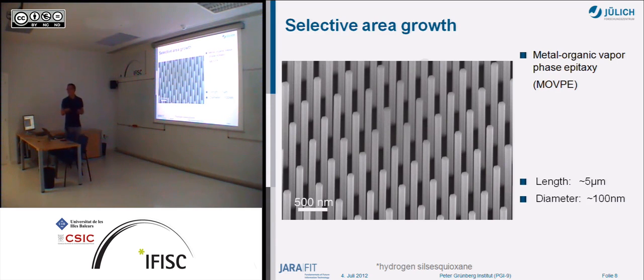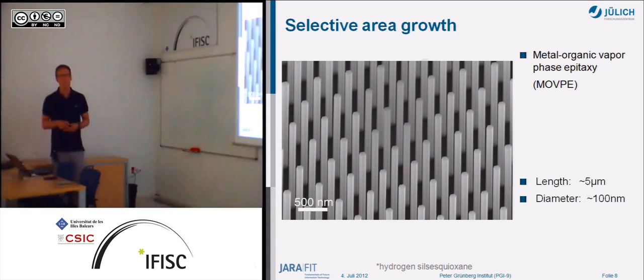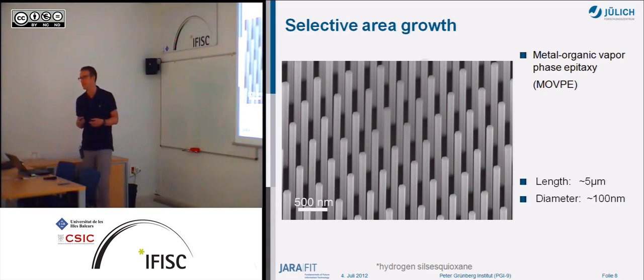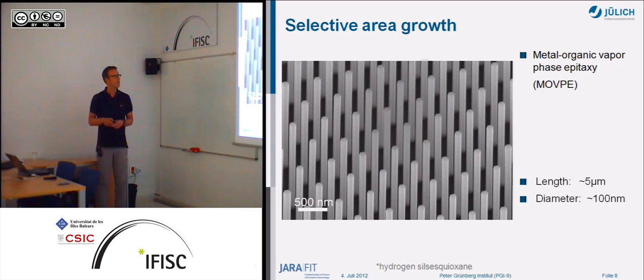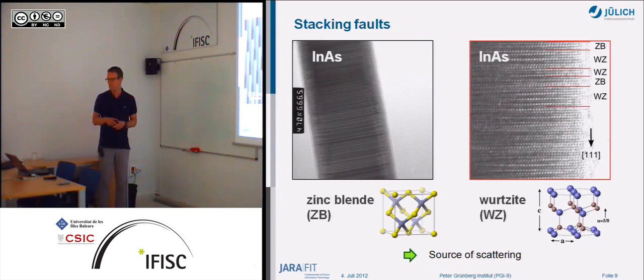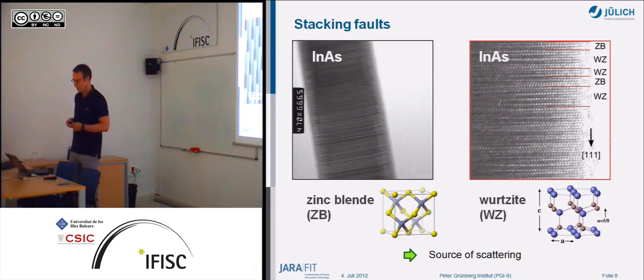The growth depends on the distance and so on, but in general the diameter is around 100 nanometers, depending on the growth parameters. And the length can be up to 5 micrometers. So those are the dimensions we have.